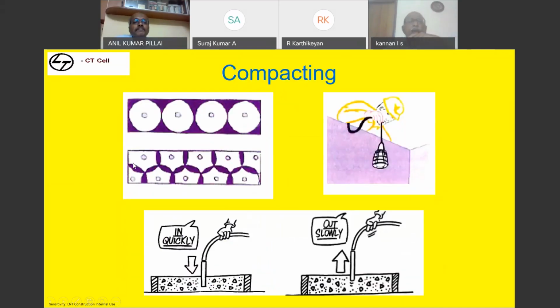Now, you are seeing the top 4 circles and the bottom some overlapped circles. When I'm inserting a needle here, the compaction happens only up to this. This all looks like uncompacted surface. Suppose I'm compacting a slab, even if I'm standing 5 meters away, I'll be able to feel the vibration. That doesn't mean the concrete at 5 meters is also getting compacted. Wherever I'm inserting a needle, the needle has a tendency to compact a particular radius of action area only. Other than that, the compaction doesn't happen. So what we need to do is overlap.